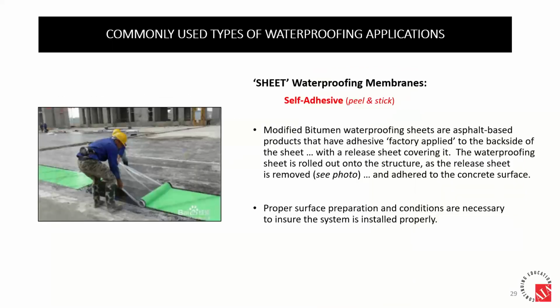The sheet waterproofing or adhesive is exactly like it sounds, and you can see in the photo, these gentlemen are pulling a backing off and trying to evenly roll this out with a properly prepped surface to make sure that it adheres. One of the things that you'll notice here is that in all cases of sheet waterproofing, there are going to be seams, and that is a common area where you might have a failure. The other thing to think about with this type of waterproofing strategy is that any mechanical disturbance on the surface can puncture, tear, or delaminate, meaning it won't stick.